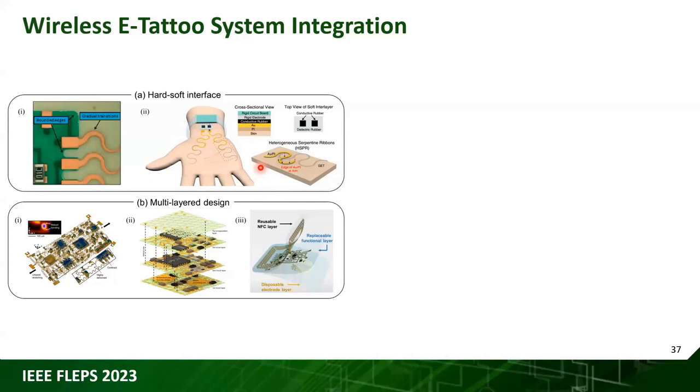And the gold-graphene contact resistance is only 1 ohm, very small contact resistance, well known. But then the gold can be soldered, or it can connect to a watch easily, right? Graphene, no way you can solder or directly contact it. And we proved both numerically and experimentally that this kind of hetero serpentine is as stretchable as a homogeneous serpentine. So serpentine, again, is not material dependent, it's geometry dependent, stretchability and softness.